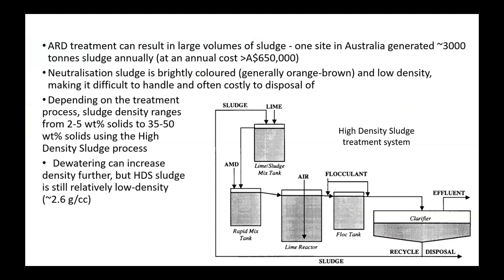The volumes of sludge can be big. One site we worked at generated about 3,000 tonnes annually. It's bright coloured, so it's not something you can hide easily. Often it has quite low density and is quite sloppy, so it can be difficult to handle and costly to dispose of. So initial treatments can have as little as 2 to 5 weight percent solids. If the high density sludge process is used, which is shown on the bottom right there, which is just where you recirculate the sludge back through the neutralisation tank, that increases the density of the sludge to 35 to 50 weight percent solids, but that's still a lot of water.